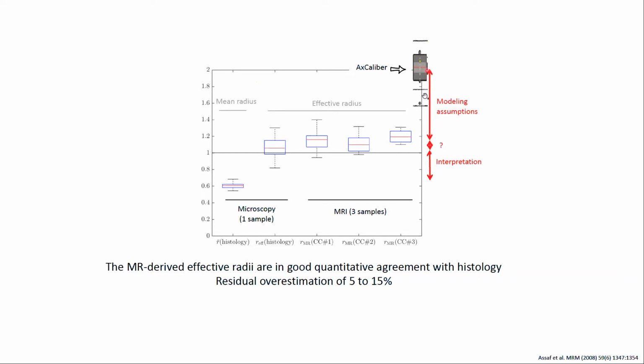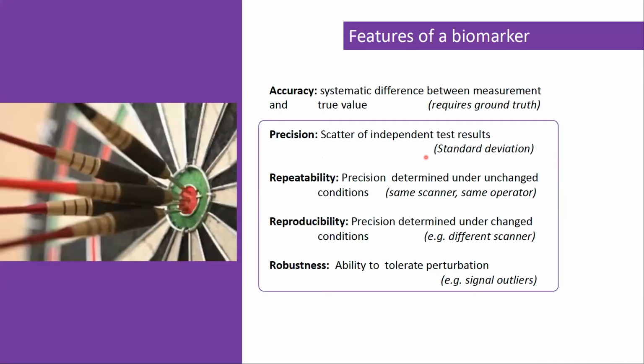If we compare our results to previous models, we can see that there's a strong reduction of the overestimation because we have fewer modeling assumptions. We don't have to deal with the extra-axonal space, and that improves our precision, our accuracy. However, the residual overestimation, which is about 5 to 15%, remains questionable, and probably many other confounding factors need to be addressed to explain this.